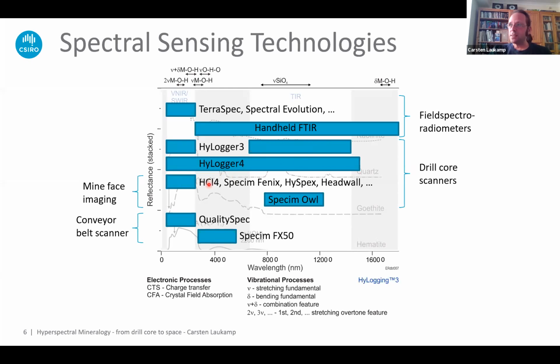Then there are other drill core scanners. So I should say also, I didn't mention it before, the HyLogger is a line profilometer. It collects basically in a stepwise function, every half centimeter roughly, one spectrum. So it's not creating an image, it's just collecting points. But there are a number of different imaging spectrometers, and I believe also in Britain you have access to these ones. Imaging spectrometers where you create basically an image of your drill core, of maybe the center 3-4 centimeters of your drill core, at a very high spatial resolution. So that would be like in the half millimeter resolution, maybe per pixel size.